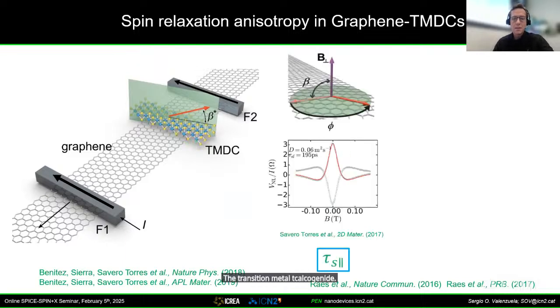So simply, we use graphene as a channel, and in a region in which we intercalated the transition metal dichalcogenide. And then, with these experiments, we see what is the spin lifetime in plane and what is the spin lifetime out of plane, by combining all of these experiments here. So we start with a model system in which we have the 2H transition metal dichalcogenide.